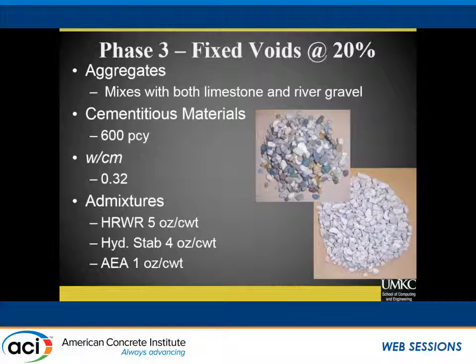So the thing we like to do, or what you should do if you're trying to look at direct effects, is we're going to fix the voids, which means every single cylinder, every single beam, the fresh material is weighed out, and then we've got a hydraulic press, kind of looks like a can crusher, loaded in a tube. It presses it down. No humans touch the Pervious, so we pop out uniformly compacted cylinders that all weigh exactly what we want them to weigh, so our variability is low.